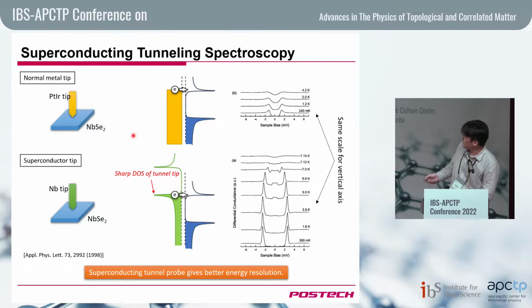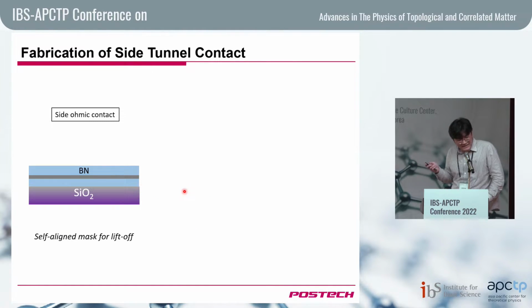If, for example, you are to study the density of states of some superconducting niobium diselenide, you can use either a normal STM tip or a superconducting STM tip, but the superconducting STM tip has a very sharp density of states in energy. So you have better energy resolution, because the dI/dV, the differential conductance peak, will happen only when this sharp density of states peak aligns with some feature inside the niobium diselenide density of states. So that's another good thing about using a superconductor as a tunneling electrode.